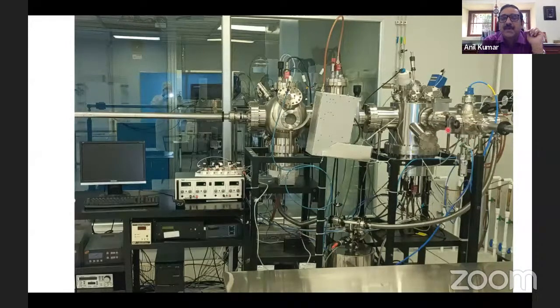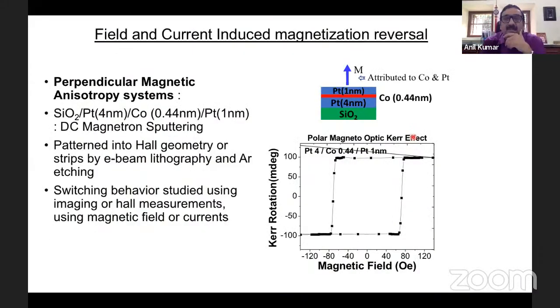You load the sample through a load lock, and then you do the deposition inside, and the base pressure is always on the better side of 10 to the power minus 8, and you can bring the system down to 10 to the power minus 10, minus 11 millibar vacuum. Now with this kind of a structure, let us deposit some films. Say I have a silicon dioxide substrate. I show only silicon dioxide here. You deposit 4 nanometers of platinum. Then you deposit 0.44 nanometers of cobalt, and then cap it with 1 nanometer of platinum. Now what I measure is something called the magneto-optical Kerr effect.